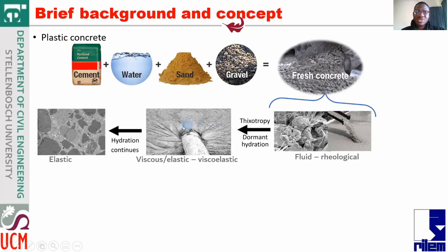And as hydration continues, the viscous properties continue to reduce, as the fluid properties reduce, while elastic properties start to increase. That is, it has pronounced viscoelastic properties, and then later more elastic properties when it hardens up. Then the question comes to mind: when do these plastic properties tend to end? It is generally assumed to be around the final setting time.